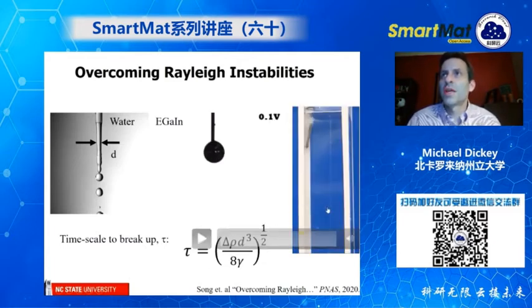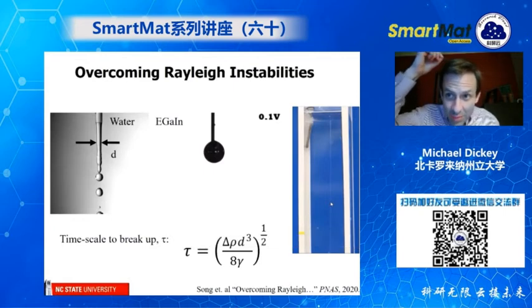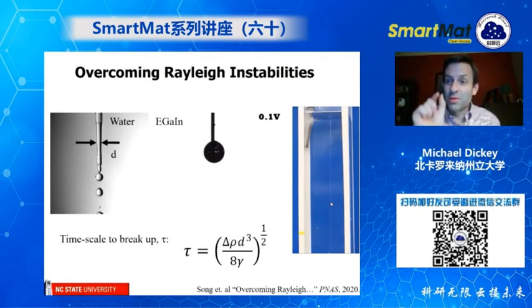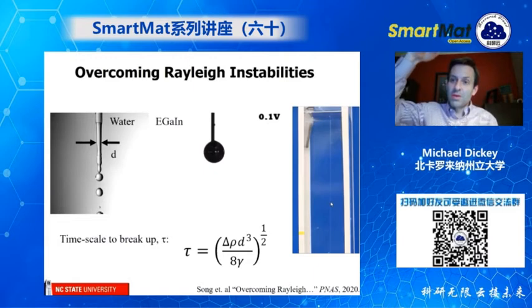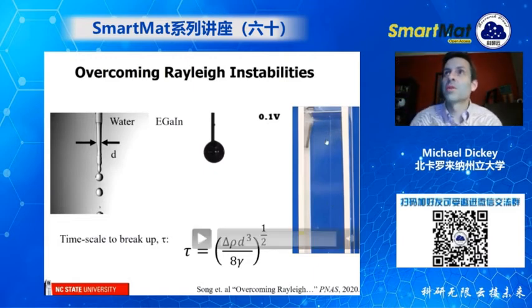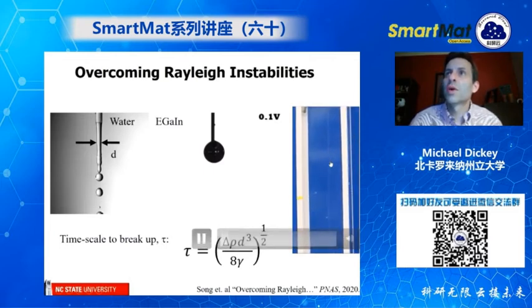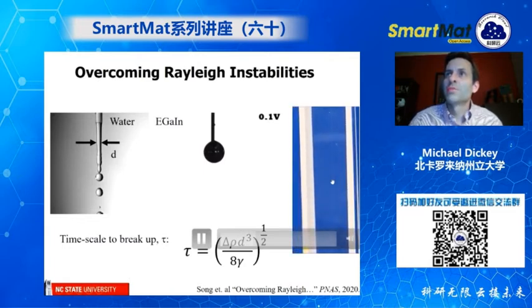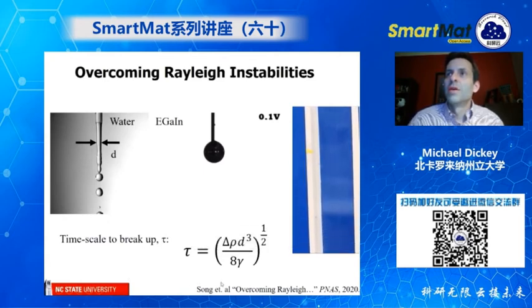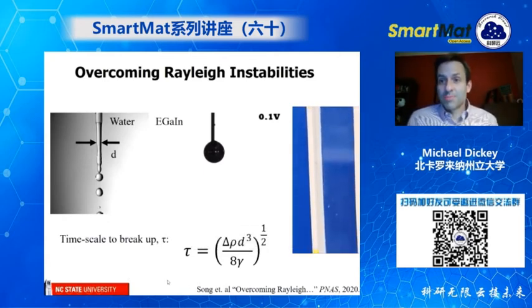We found the tallest container that we could find in our lab, and you might be able to see this very thin line. This is the liquid metal wire. This is like the size of a human hair. So if I pull out my hair, it's made out of liquid metal. So it's 100 micron diameter, and it's about, not quite a meter, maybe half a meter in length. So as you'll see in this video, here's the nozzle, and let's see if this will work. So I'm pointing to the wire. You can see it's very, very long, and it's flowing at a very slow velocity, and it flows all the way down to the bottom of this tank. So this is pretty interesting.